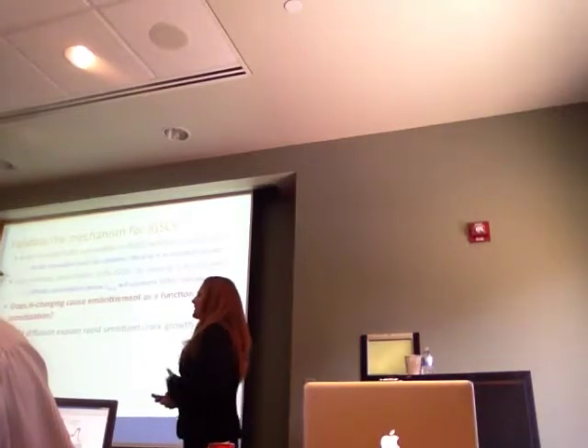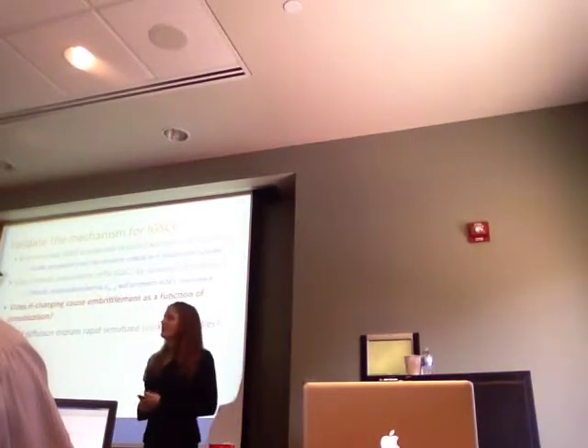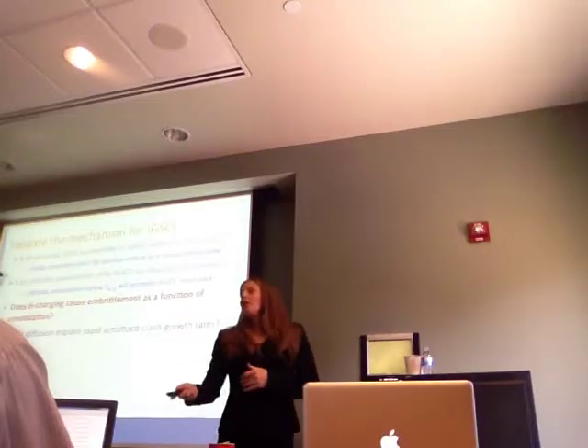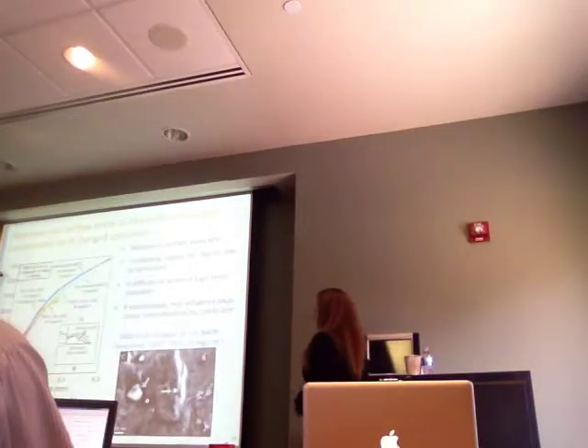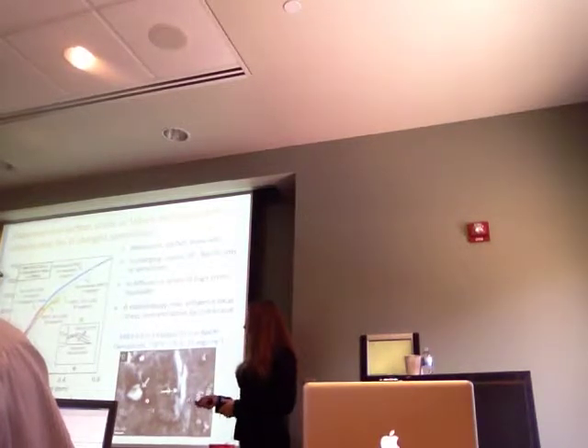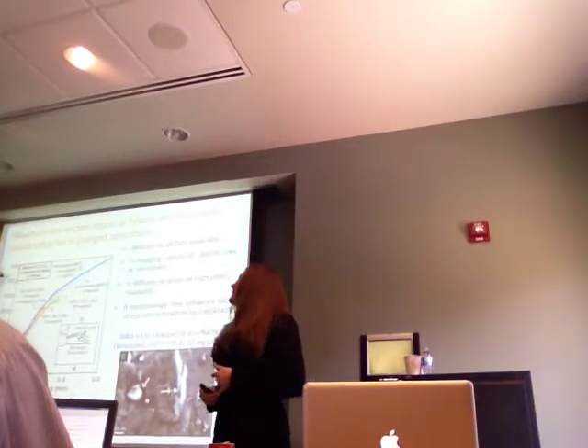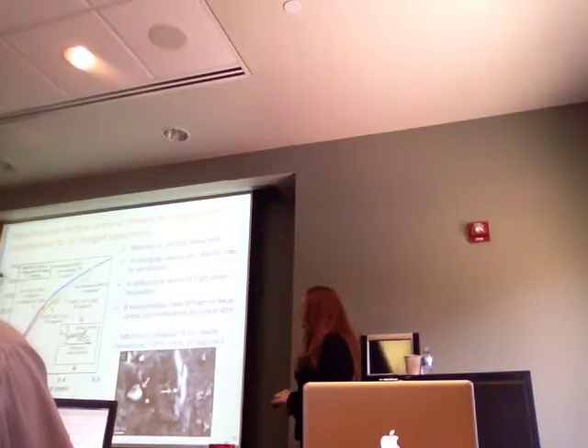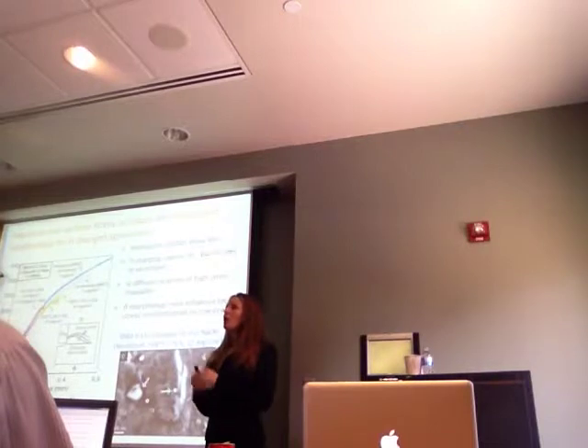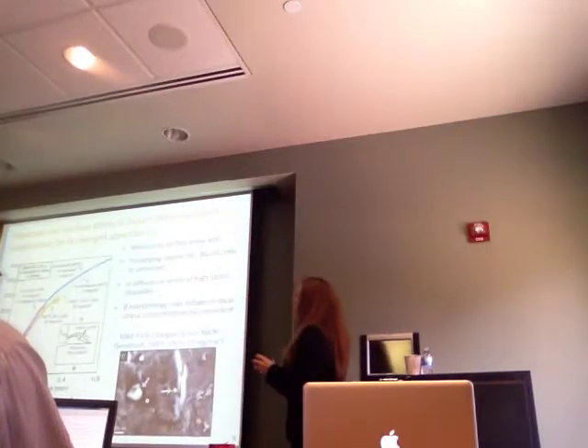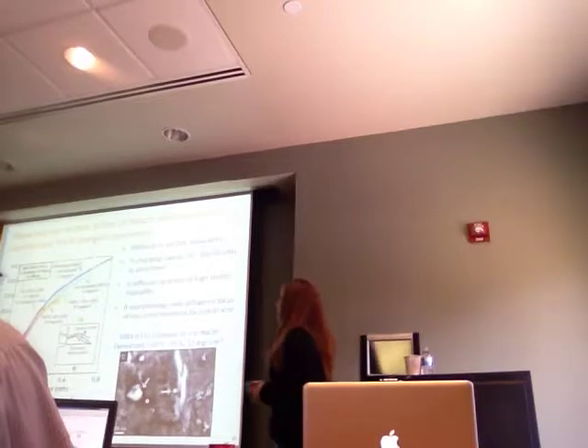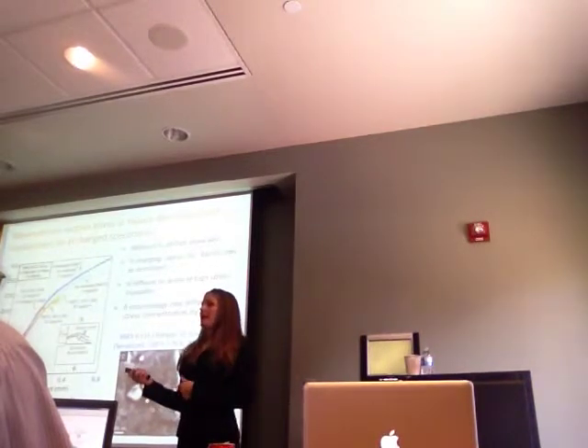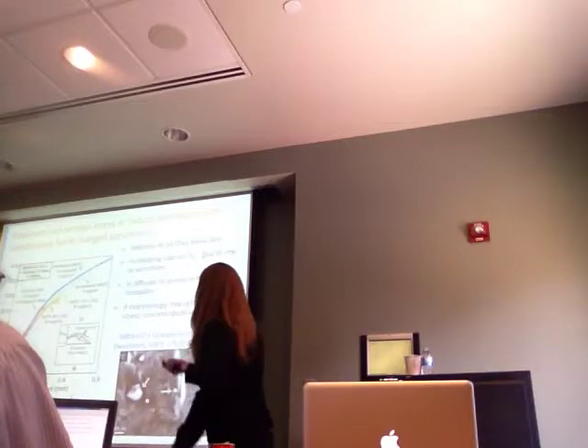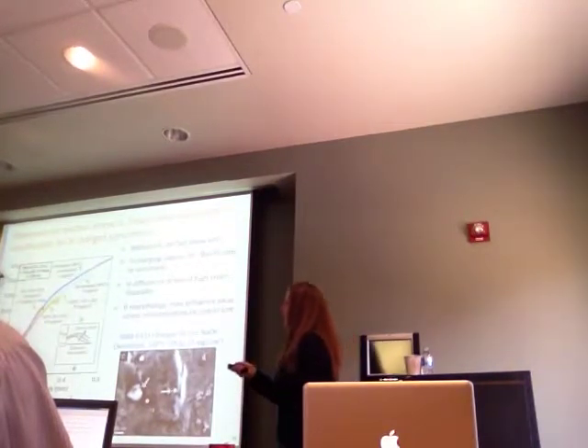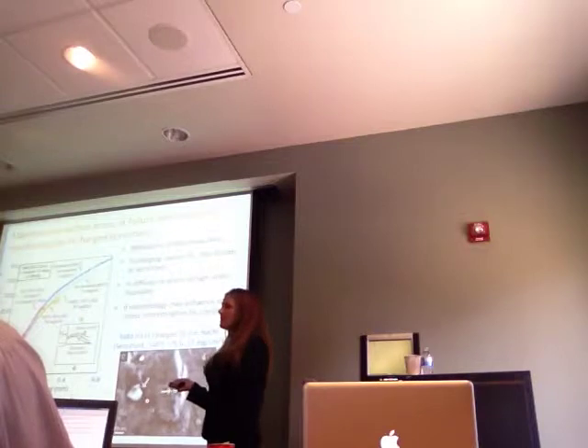So the next thing we want to look at is if hydrogen charging can cause embrittlement as a function of sensitization. So what we've done here is we've taken several small specimens that are about 2.2 millimeters, and we put them in sodium hydroxide. We've left them there for 16 days, and during that 16 days, hydrogen penetrates the microstructure, and then we load these specimens in air to see if the hydrogen causes embrittlement. And so what I've plotted here is the stress versus displacement during our loading of these specimens.